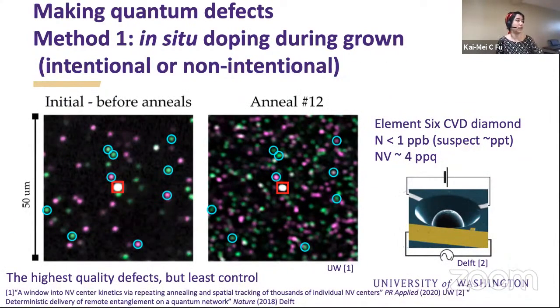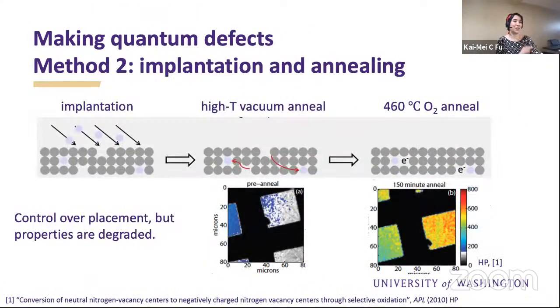Okay, so this is if you just take material that's grown in the highest purity, but we don't necessarily want to just get what we get, right? The whole point, or one of the big advantages of using defects, is the idea that we can put them in the material at will, right? And one very powerful way to do that is via implantation and annealing, right? When you implant the sample, you implant the nitrogen. It doesn't just create the nitrogen, it actually creates a lot of displaced lattice atoms. And then you do an anneal where the